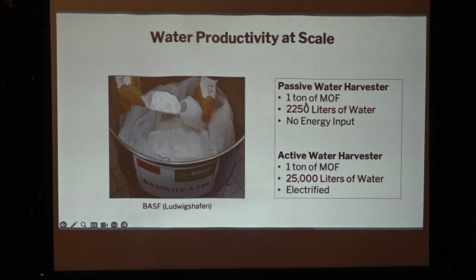Okay, so what does this mean? It means that if I don't use any electrical input, any energy input aside from sunlight, if I have 1 ton of MOFs, which is no larger than this table, I can give you 2,250 liters of water per day. And that MOF will be sitting there for 6 years, no maintenance necessary. No energy input aside from sunlight. Now, if you're impatient and you want more water in a shorter period of time, you can electrify it, and 1 ton of MOF will give you 25,000 liters of water per day. Day after day after day.